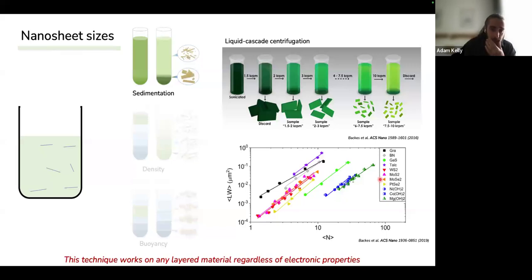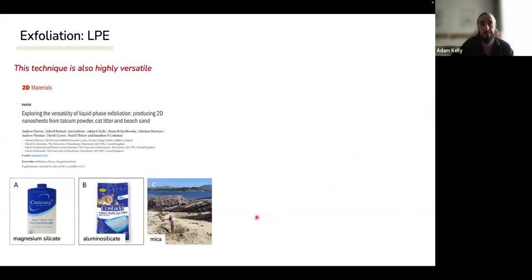But what we do find with this process is that the thickness of the nanosheets is related to the length of the nanosheets. So this means if we want to get large nanosheets, they're also very thick. And if we want monolayers, for example, they tend to be very, very small in lateral size. So that's just one of the things that we have to deal with using this process. So this technique is extremely versatile.